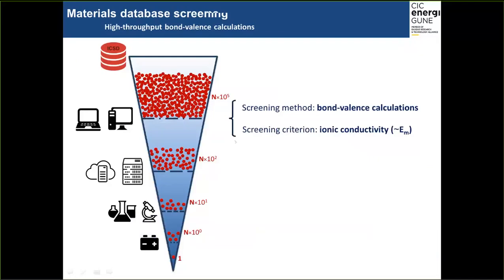So this allows us to perform high throughput calculations and rapidly screen material databases such as the ICSD, going from tens of thousands of candidate compounds to a few hundred. Key elements here are the choice of a very fast computational screening method, in this case the bond-valence method, and the choice of the screening property to be assessed. In our case, we consider the ionic conductivity, which we estimate from the percolation energies computed with bond-valence.